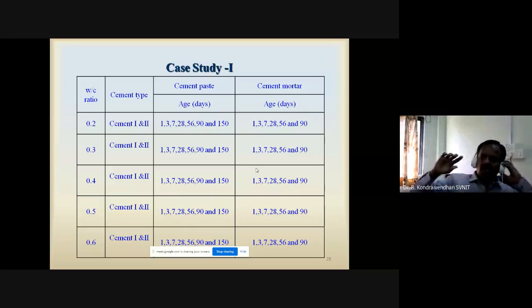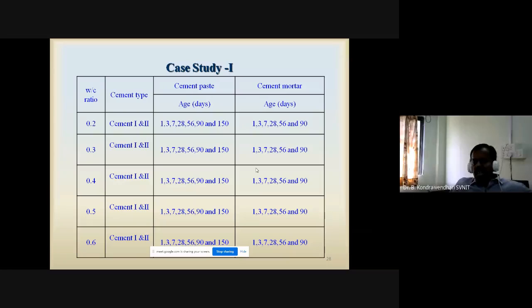Okay, so far I have explained how to use the mercury intrusion porosimetry, but now I can explain how one can perform actually. Actually, this concrete is a very complicated system. This is what I mentioned. So we can predict the compressive strength, permeability, everything through the pore structure parameters. As I mentioned earlier, the pore structure parameters are R5, D and P. P is the permeable porosity, R5 is the mean distribution radius, and D is the dispersion coefficient.